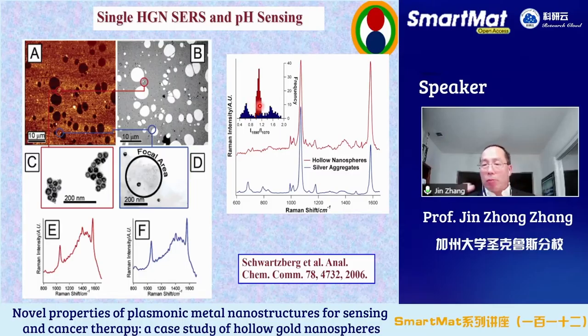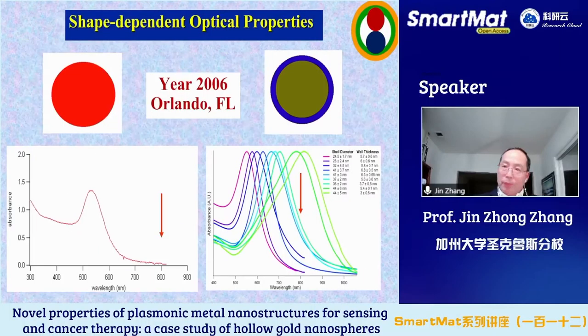We measured hundreds of particles and did statistics. The red is from HGN, the blue is from silver. So the HGN is very uniform in size distribution. It gives a much better SERS spectra. And this was also published. And Adam graduated. So that could be the end of the story, right?